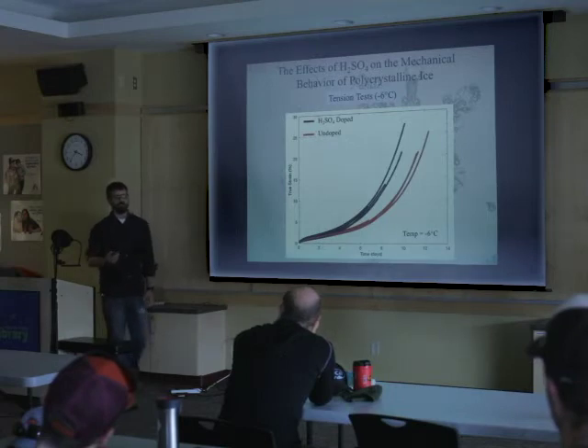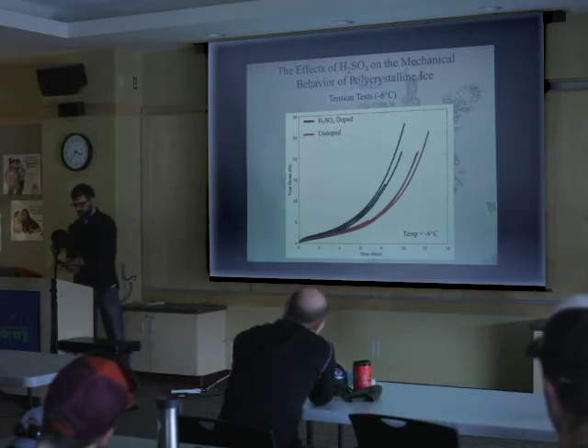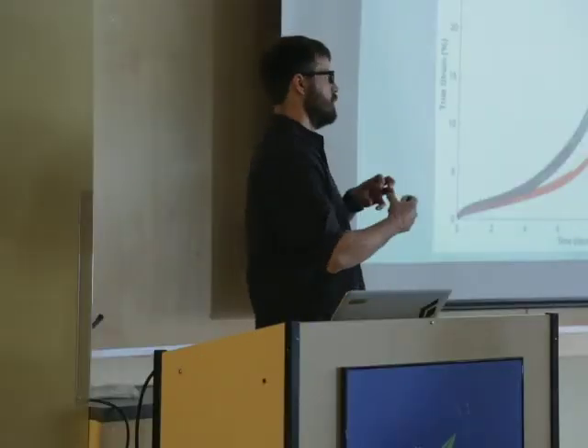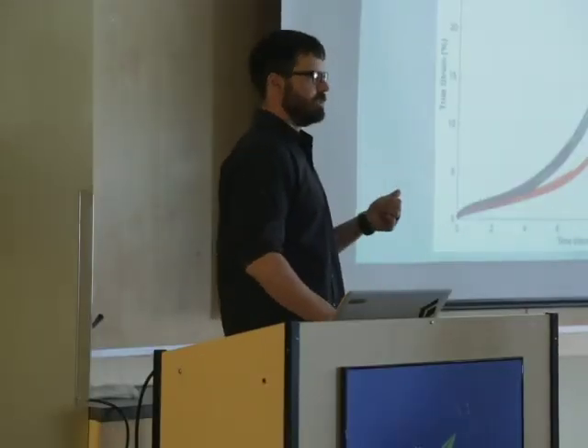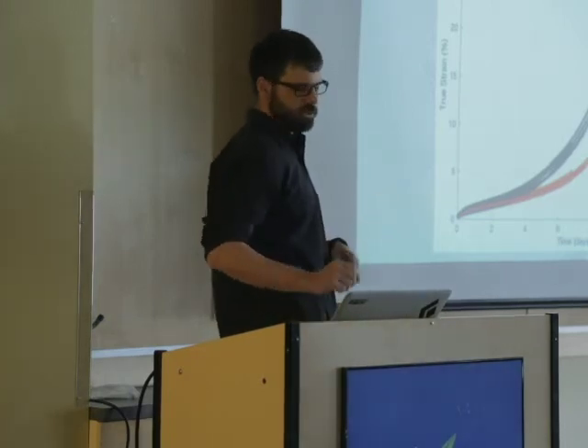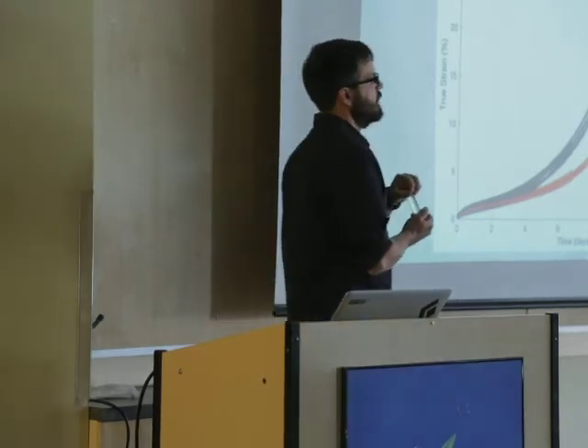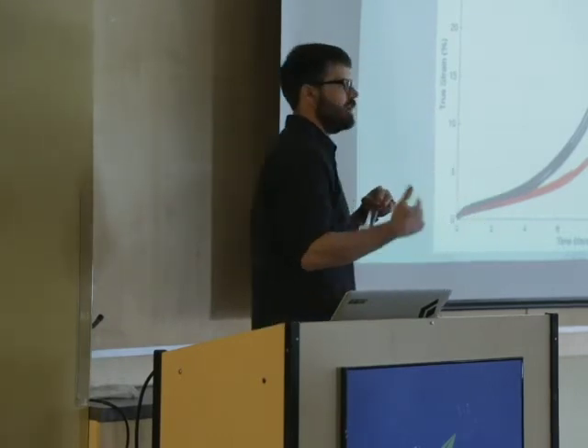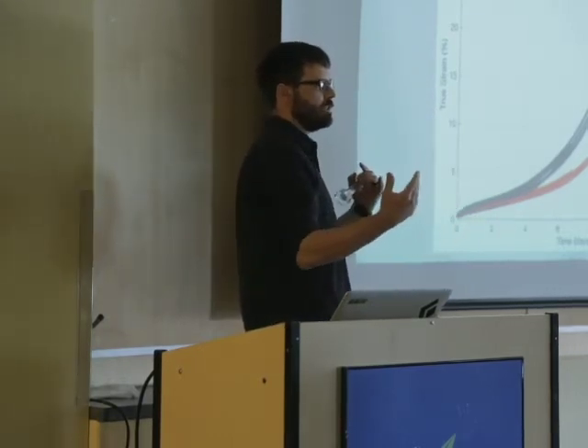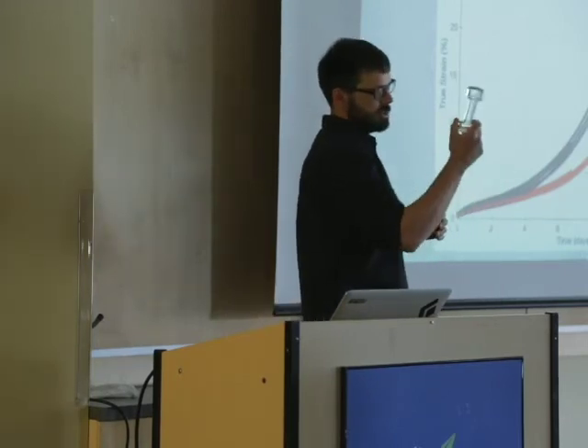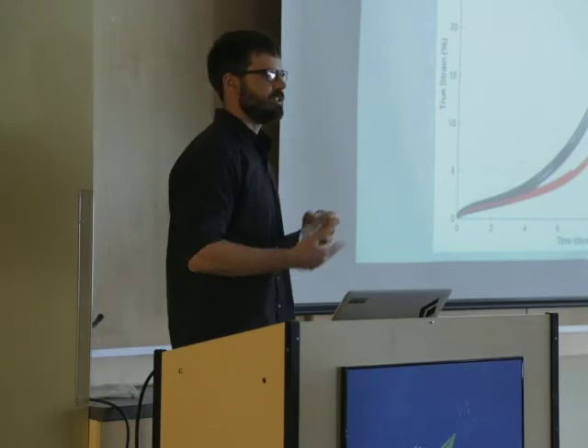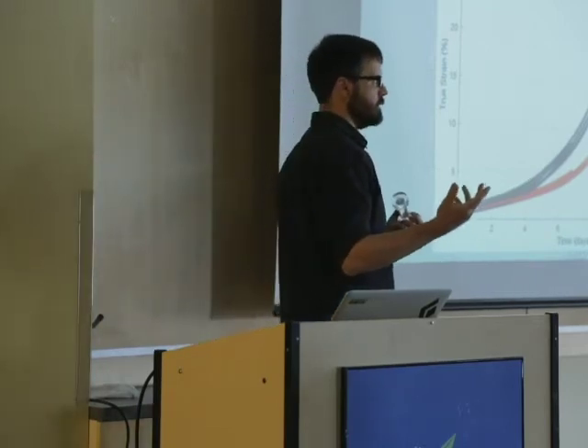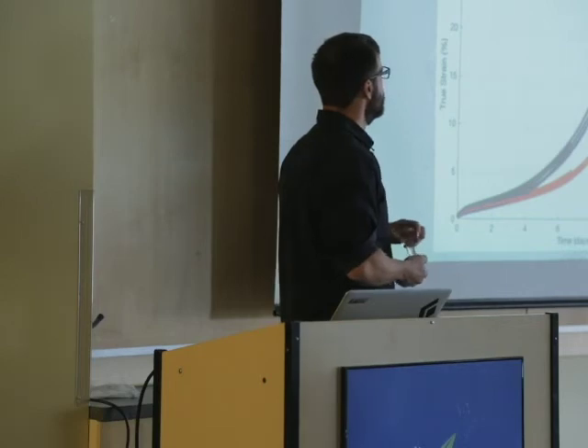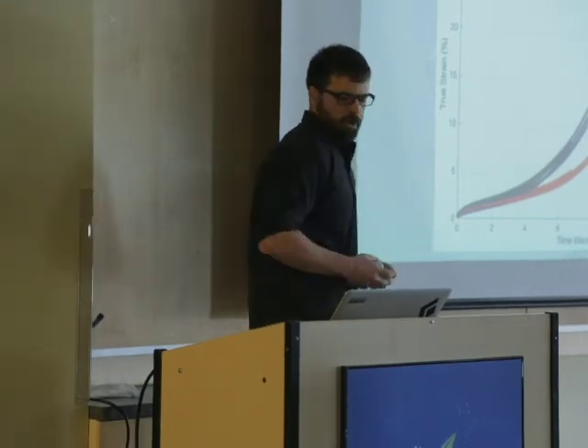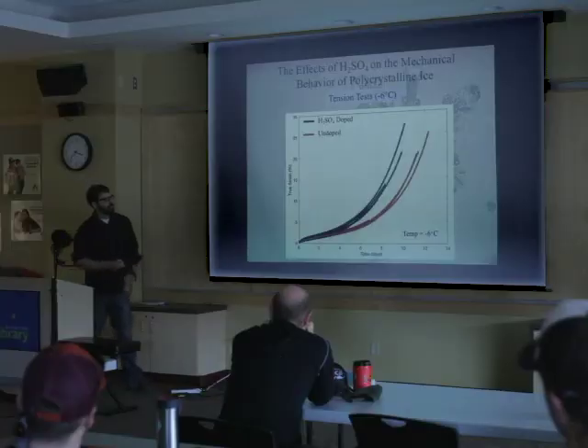So the thing that makes creep really interesting to study when you're talking about something like ice is that creep rates and that slow deformation are really, I want you guys to remember this, time and temperature dependent. So if you put just a light load on something and give it a high temperature, being near its melting point. So in our world, ice and snow is always near its melting point. The steel beams in this building are nowhere near their melting point, right? So you wouldn't expect something like creep to be an issue for steel, but for ice in our world, it's a big issue. So it viscously flows, it creeps. And it's time and temperature dependent. So these were relatively fast tests, only 12 days long, because we're at a really high temperature, -6°C.